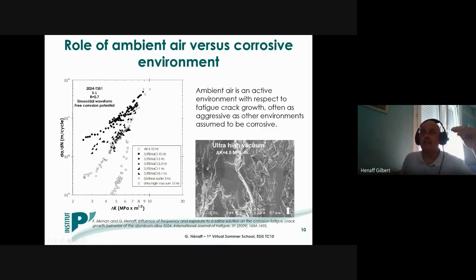And what you can see is that the fatigue crack growth rates in air, in most cases, are similar to the fatigue crack growth rates obtained in liquids, especially at low frequency. And in that case, we need to move to quite high frequencies, typically 5 to 10 hertz, in order to induce an environmental effect which is larger than the environmental effect induced by ambient air. So that means that in many cases, ambient air is at least as aggressive as other environments which are assumed to be corrosive.